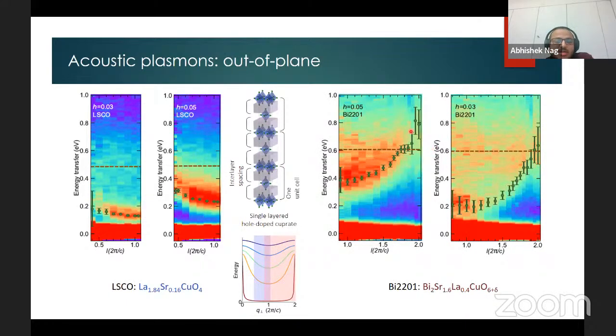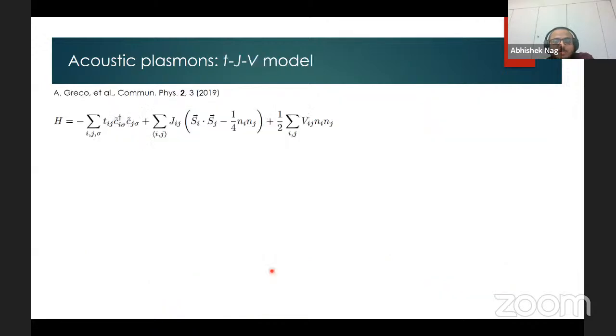And here again, you can see that this mode disperses quite a lot in Bi2201. Now, if you ignore the energy differences for a moment, you can indeed visualize the dispersions of these excitations in the out-of-plane direction with a periodicity that is expected for the acoustic plasmons.